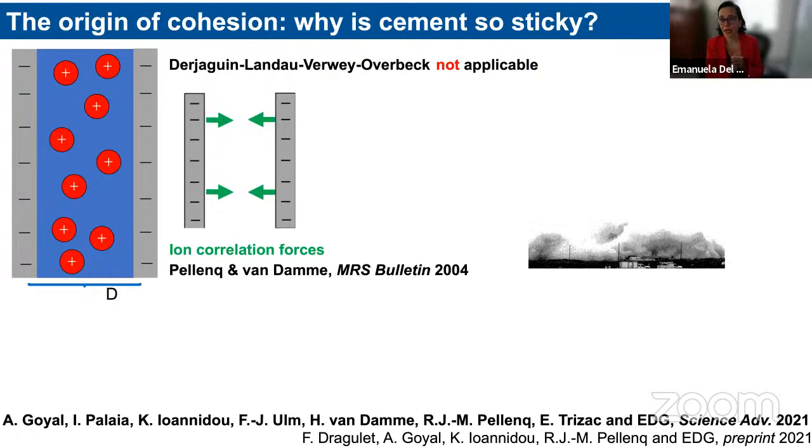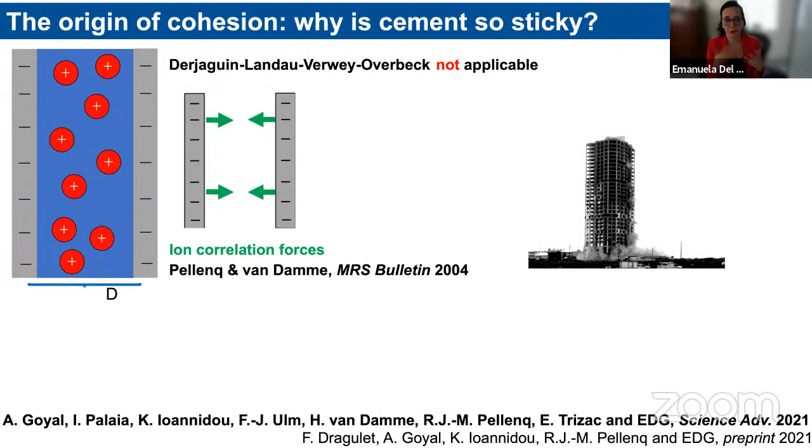So if you consider theories like the DLVO for the range of surface charges that you have in cement and the presence of mainly divalent and multivalent counter ions, basically the DLVO would give you just repulsion. So definitely your building would not stand up. There has been therefore a development and understanding that actually the cohesive forces come from whatever is neglected in this theory, which is the fact that ions in the solution intercalated between the calcium silicate hydrate surfaces are actually